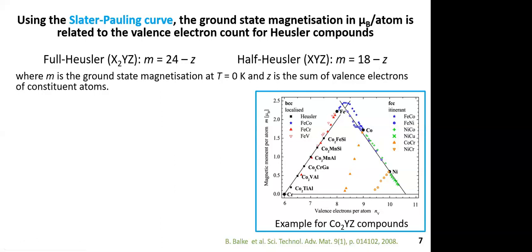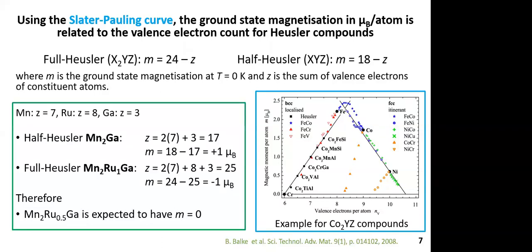So now to give you an idea of how we can do this calculation to predict a zero-moment half-metal, we take first a half Heusler material, which is manganese gallium. And when we calculate m, we find that we get +1 mu B. Then for a full Heusler, which is manganese 2 ruthenium 1 gallium, we obtain -1 mu B. So by tuning the ruthenium content, we can achieve a composition which can lead us to an m equal to 0.